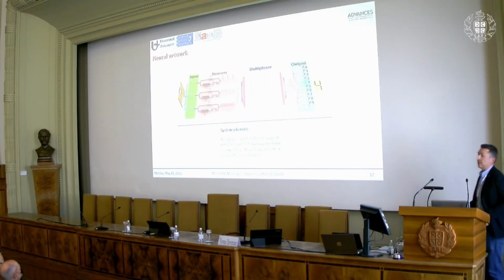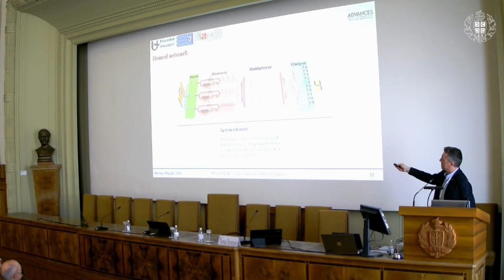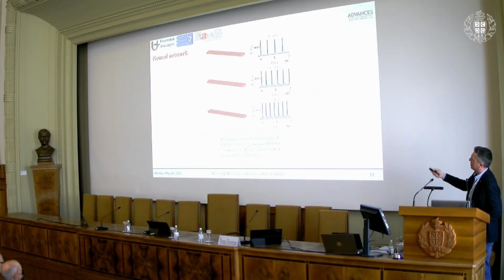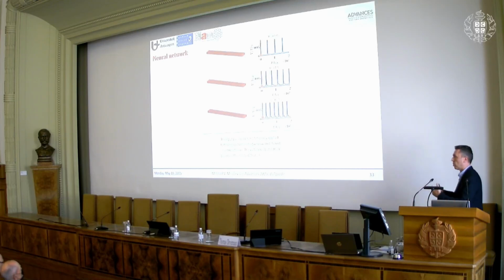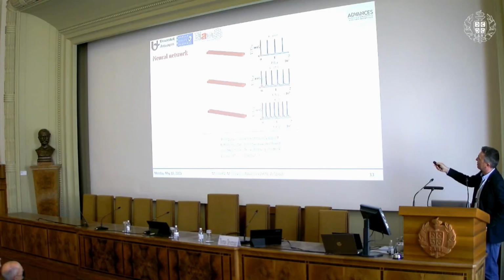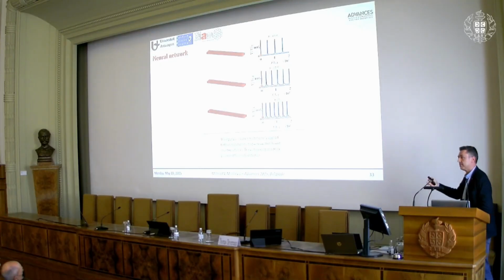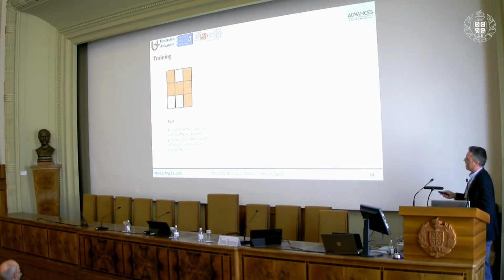So now we decided let's make a neural network. I'll speed it up, I have only 2 slides. But basically we use the same stripe, but shunted with different resistors. If I take the same stripe that I just showed you with 3 different resistors, this is in some theoretical units, but let's say it's about 1 ohm, 2 ohm, 3 ohm, then we get different frequency of spikes in the same time period for the same applied current. So now what I do, I will skip this, I take an image. In this case, it was a simple 3x3 image, an image of the number 4.